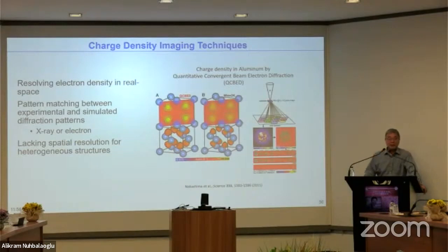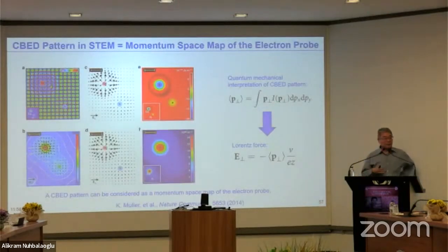Electron beam, convergent beam electron diffraction has been developed for decades, and it also offers a technique to determine charge density, using fitting of structure factors, which can give very nice measurements of the charge density. But again, this is a space average that depends on how big the probe size is. For this kind of CBED, the probe size is typically huge, not at the atomic scale. So that was the motivation for us developing the charge density map in the interface local structures.